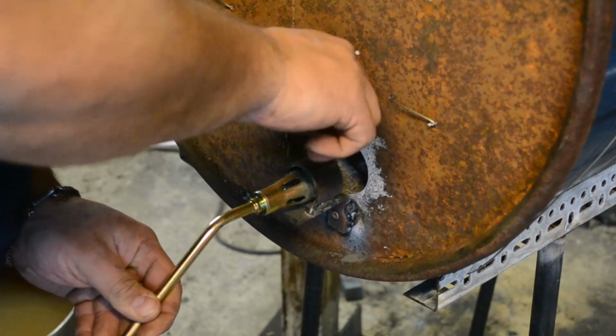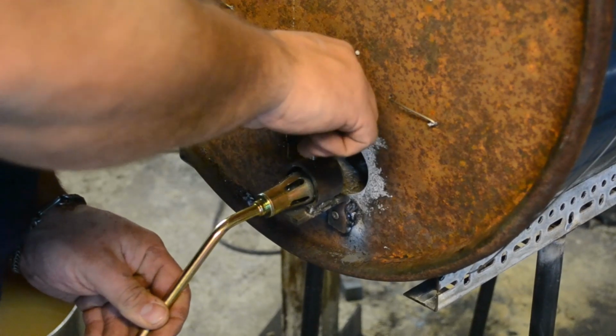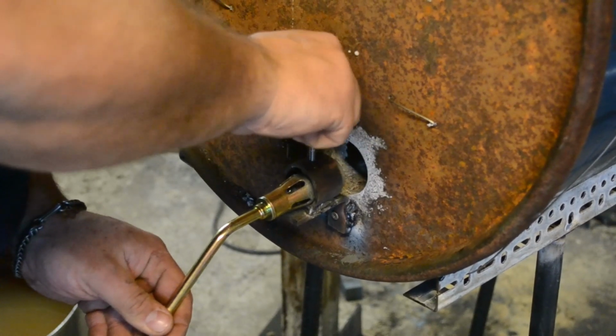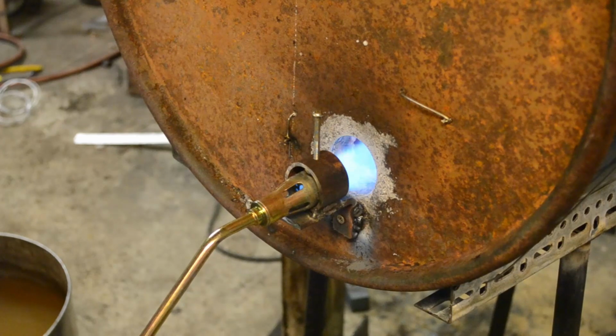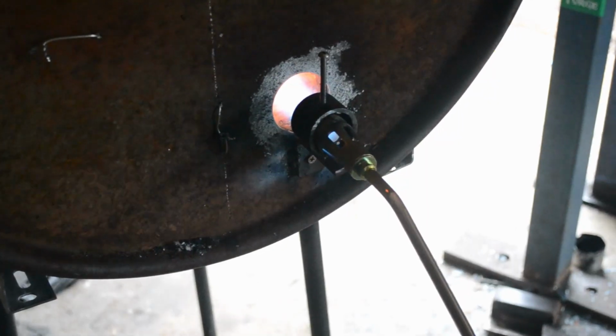And as you can see, I'm using a much smaller burner nozzle now. I'm using, I believe, a 3/4 inch, maybe a 1 inch burner nozzle, and it's set back about 1 inch from the orifice, and you can see that the flame is now perfectly registering, and we've got that really nice even heat.